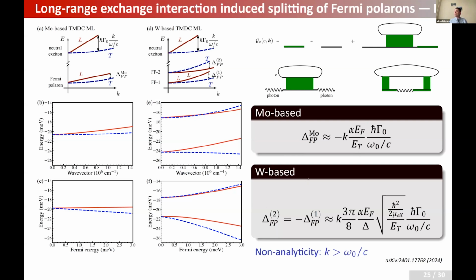In tungsten-based materials, in tungsten-based TMDCs, the situation is a little bit more complicated. Actually, the factor that plays a role here is now the ratio between the Fermi energy and the splitting between intra- and inter-valley trions. So this contribution is expected, at least in the theory, to be the largest. So we propose to measure these splittings and indeed to justify the Fermi polaron approach, or if the splittings turn out to be zero, then probably the trion approach would be more accurate for these systems.